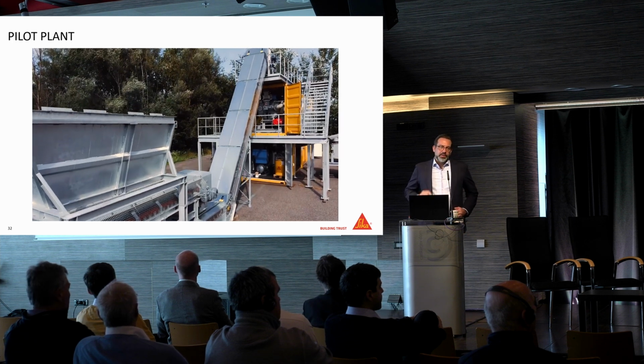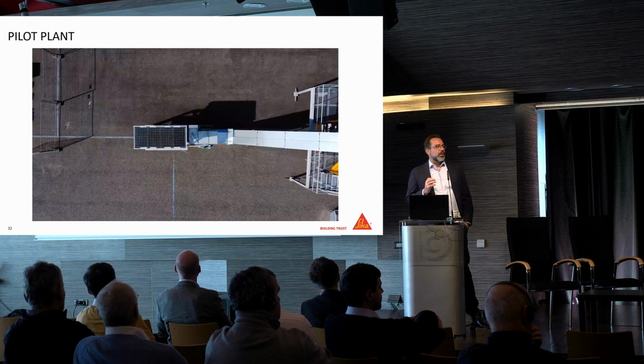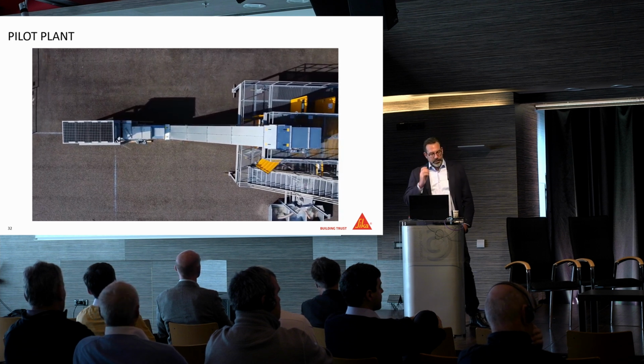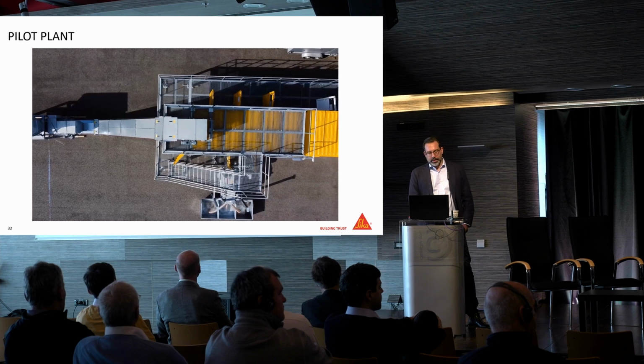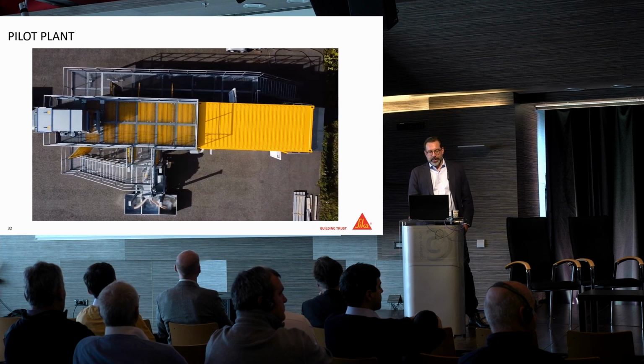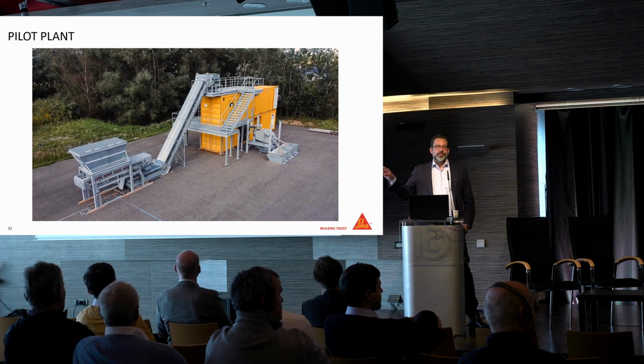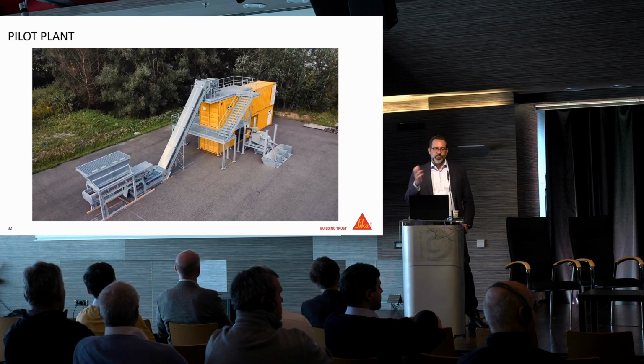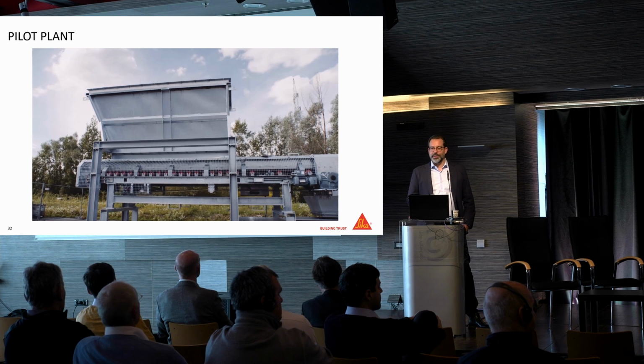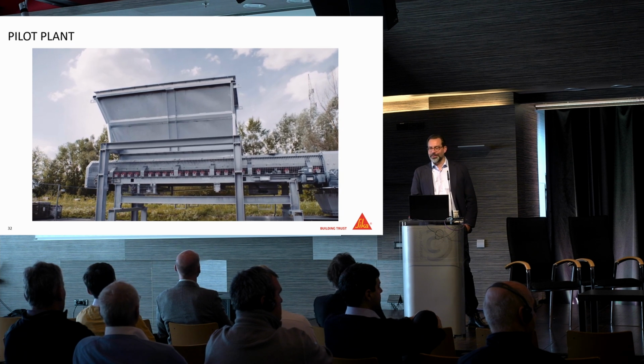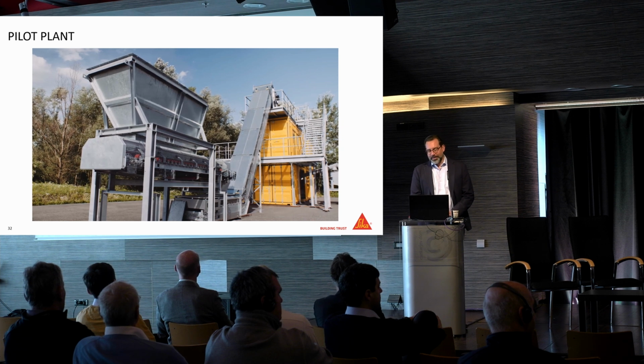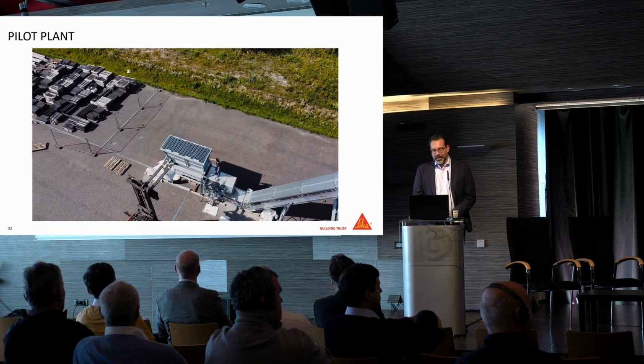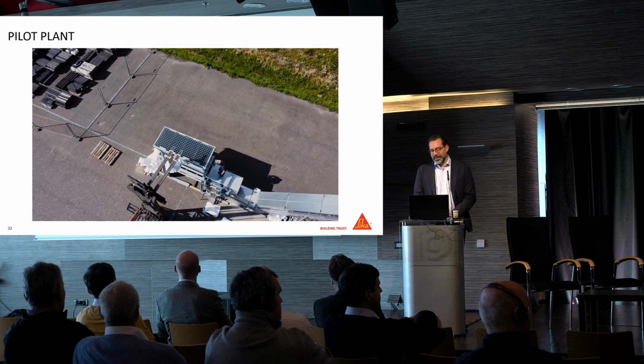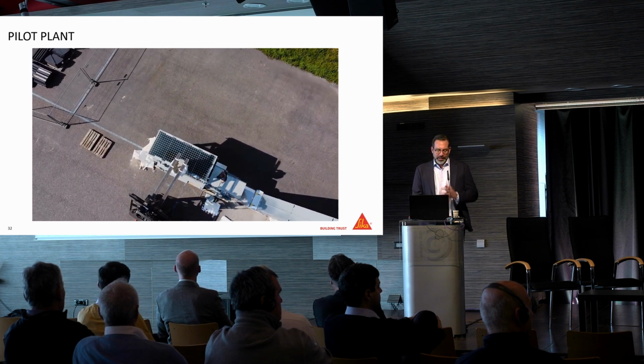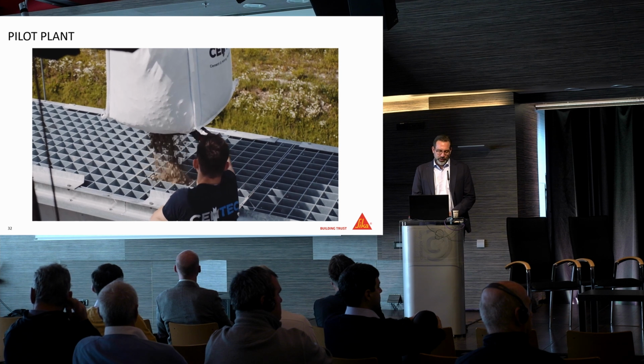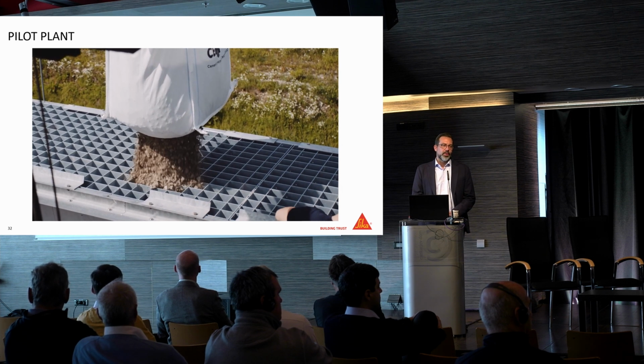So the idea was first that we install kind of a mobile plant, in 4 shipping containers. And the idea was that we bring it from customer to customer, but in fact we only moved it once, and we saw it's much easier to bring the concrete demolition waste to the plant than the plant to the concrete demolition waste. So what you see here is the hopper. This is where the material gets filled in. So this is an example of pre-crushed concrete demolition waste. You see here it's pre-crushed down to smaller than 40 millimeter.